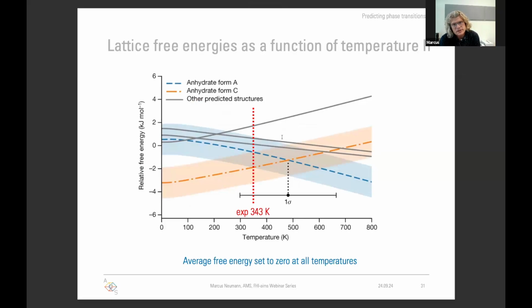The stripes have a diamond-shaped crossing region, and the 1 sigma interval of the prediction of the phase transition is somewhat related to the diamond shape. You also see the experimental phase transition temperature, 343 Kelvin, which actually falls into the 1 sigma interval of the prediction of the phase transition. But there's a big but, so the error on the phase transition is still something like a couple of hundred Kelvin. That is a lot.